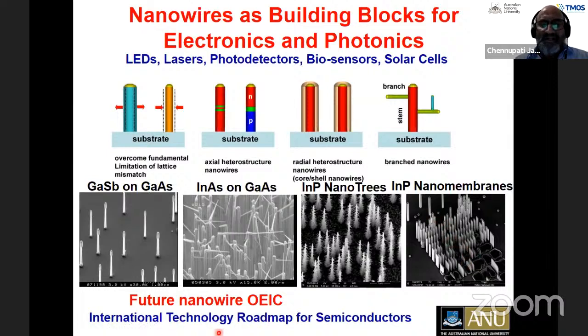But most importantly, the International Technology Roadmap for Semiconductors, the people determining what technologies are needed for the next generation electronics, have identified nanowires as a key technology component for electronics as well. So if lattice mismatch is no longer an issue, can we really grow III-V nanowires on silicon? In fact, IBM Zurich has demonstrated indium gallium arsenide nanowire transistors on 6-inch wafers of silicon. It demonstrated excellent results, indicating that nanowires are going to play an important role both in electronics and photonics, for making LEDs, lasers, photodetectors, biosensors, and so on.